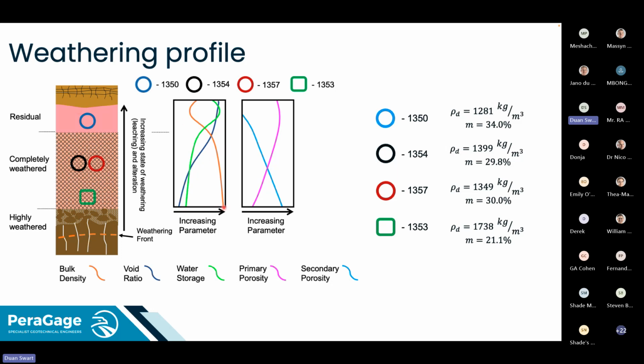And the void ratio, or the water storage here, the green one, will be inversely proportional to the bulk density, and then your void ratio generally increases all the way up. Your primary and secondary porosity are based on your relic rock structure. That will be the most open in a competent rock, and then as weathering occurs, the joints will fill up with infill, and the faces will get weathered and fall into the joint. If you continue that into completely weathered rock, your secondary porosity generally decreases to a point where your rock structure is lost due to the compaction or collapse of the residual, and you essentially have no more secondary porosity, and your primary porosity will generally increase with a decrease in compaction.